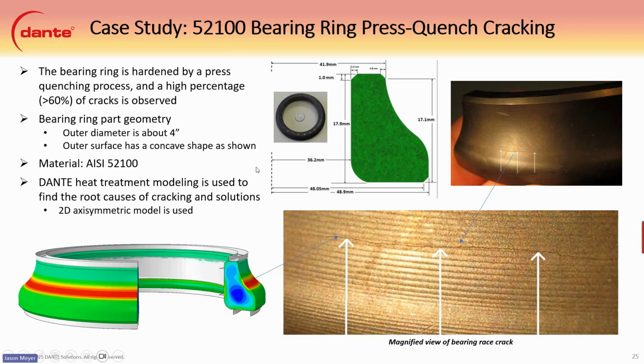The material again is 52100, and the DANTE heat treatment modeling is used to find the root causes of cracking and solutions. We used a 2D axisymmetric model for this, so we basically took this whole cross section and were able to model it in 2D, with the contact from pads on the top and the bottom, and the expander on the inside. Here's an image of the quench crack. I hope you can see that on your end. It shows the cracking along the outside edge of the race here.